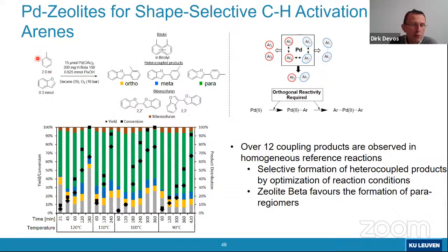If you just throw together toluene and benzofuran, you can count it, you can make 12 isomers. You can make 3 of these coupled benzofurans, and you can make the 6 bitolyls, and then you can also make 3 different heterocoupled products. Now, with all the optimizations and modifications to the system that Yannick did, he was able to increase the yields. As you see here, the yields are getting higher and higher. We are not at 100%, but still we are at pretty high yields based on the benzofuran.